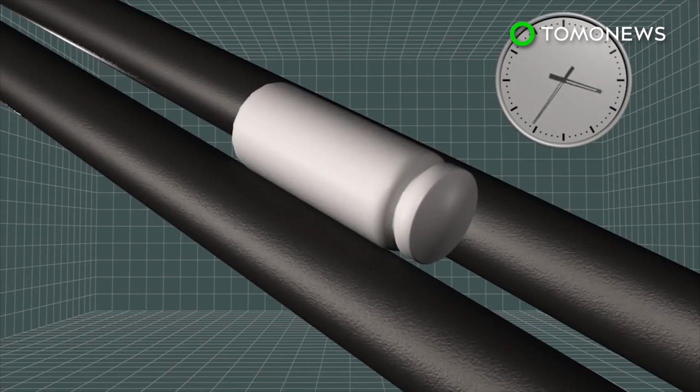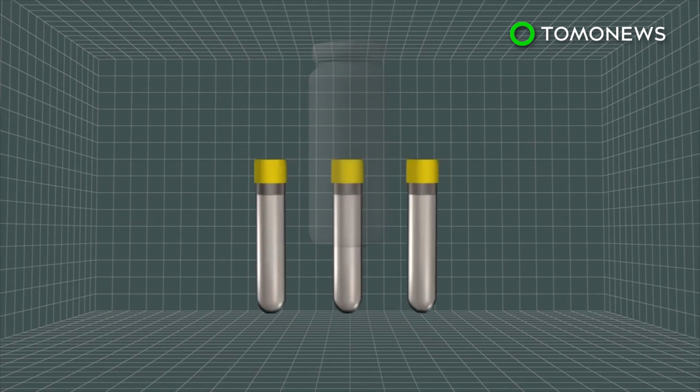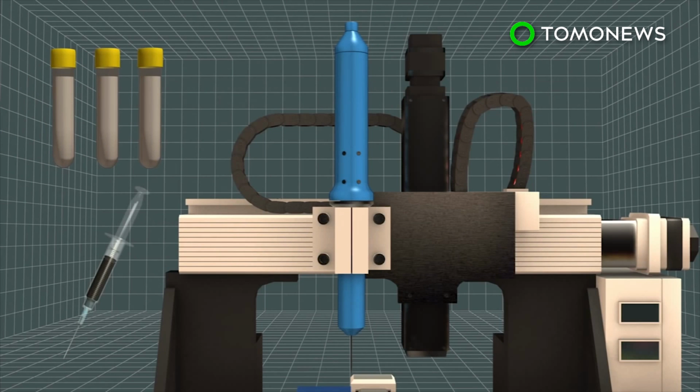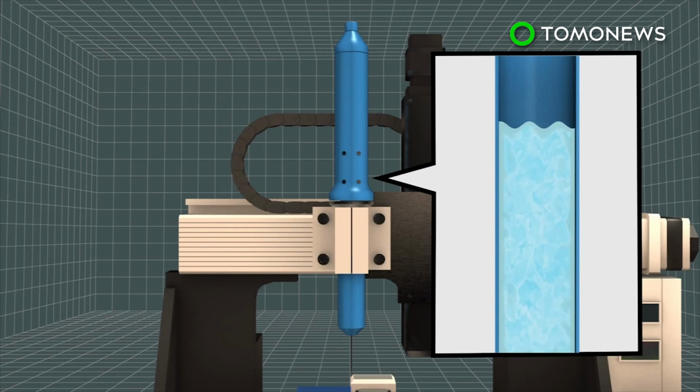The mixture is spun for 24 hours. The balls and larger particles are removed with filters in a centrifuge. The resulting ink is placed in a syringe and inserted into a high-pressure dispenser on a 3D printer. The ink is solid when unperturbed, but flows under high pressure.